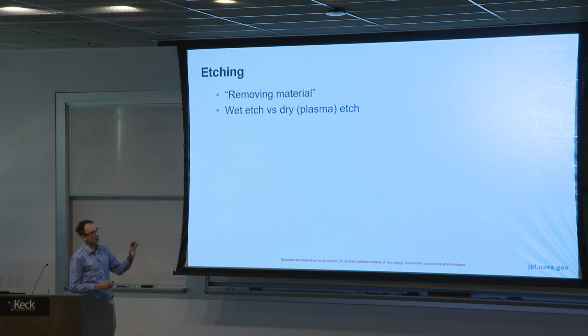In contrast, plasma etching is done in a special purpose tool where you put your wafer in, you pump a vacuum, you introduce gases very controllably, you strike a plasma, and you can bias the plasma, you can drive it at different frequencies, etc. In modern etch tools, you can also decide which gases to flow into the system. Maybe you even have too many parameters that you can tune to get the etch performance that you want.